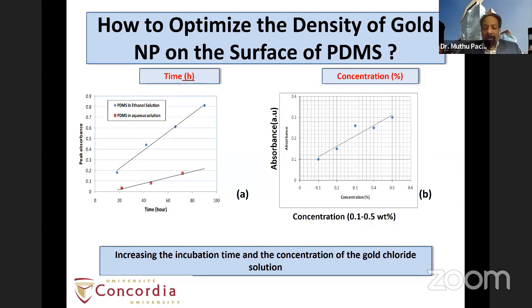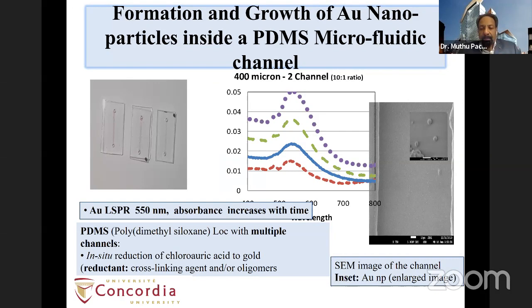And also we can use ethanol or water. One can change the different PDMS composite configurations again. So these are all various tools. We have various parameters based on the sensitivity one requires and based on the bioparticles that you want to detect. So here, you can see this is a microfluidic channel made of PDMS. You can see the red color microfluidic channel because that's where we have in situ synthesized gold nanoparticles. You can see the gold nanoparticles in the SEM picture here.